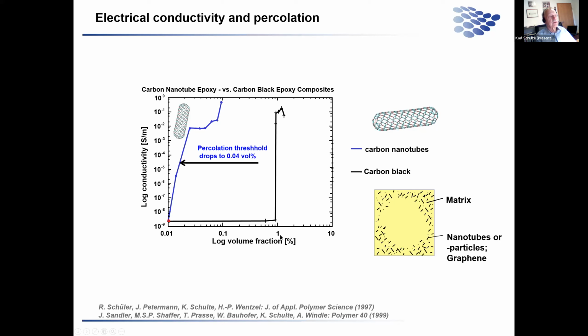We have here a very good example of what we call percolation. Percolation means we have very few nanoparticles in a matrix; they do not touch each other, therefore no electrical conductivity. But suddenly, if we reach a certain amount of well-distributed nanoparticles, in this case carbon black, we suddenly get electrical conductivity, and we call this the percolation threshold.